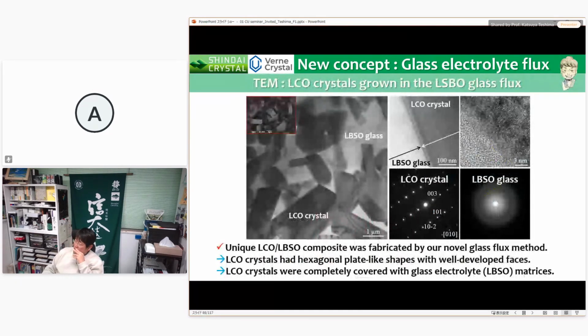As clearly shown in these pictures, a unique LCO-LBSO composite was fabricated by our novel glass flux method. LBSO is a glass solid electrolyte. LCO crystals have hexagonal plate-like shapes with well-developed facets, and were completely covered with the glass electrolyte LBSO matrices, as shown in these TEM images.